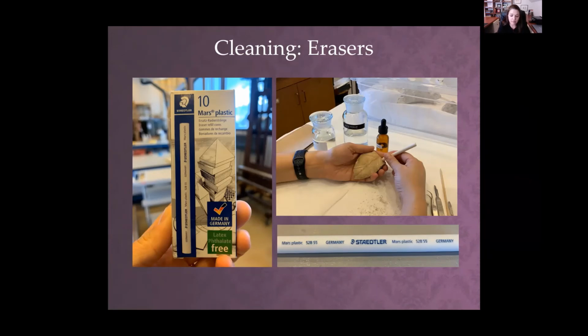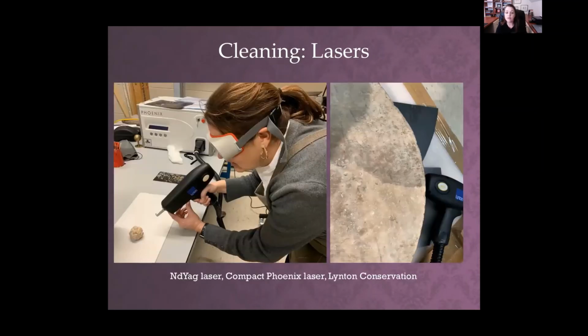So you're able to clean areas with less surface dirt more gently, whereas areas with more significant surface grime can be cleaned to a better extent, really unifying the sculpture slowly with these erasers. The erasers weren't able to do everything, and so we're lucky enough in the lab right now to have an ND YAG laser, which is by Compact Phoenix Laser from Lynton Conservation. We ended up using these on the leaves and berries, which Scott had determined were Carrara marble, so they were most likely not ancient. And then also on the base, which through Fernando's research, with the tool marks on the side of it, had been heavily reworked, probably in neoclassical times. So we know that neither one of these were ancient surfaces that hadn't been reworked or changed significantly. So we weren't as worried about over cleaning these.